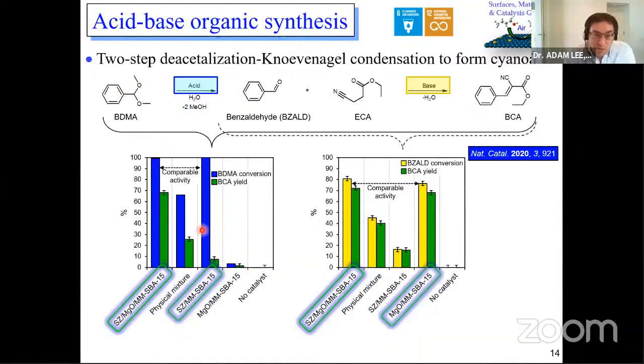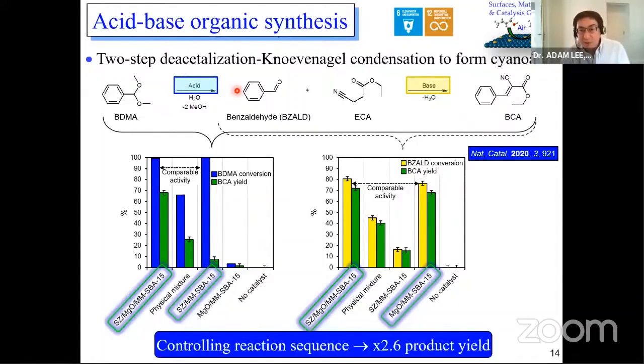And that's why the overall yield of BCA is about 70%. It is far superior to what you see with a physical mixture. So if you just take a physical mixture of a normal solid acid and solid base and put them into the same flask, you get quite poor yields of the final product. Whereas here, bringing these two sites, the acid and base site, close together allows us to do the cascade very effectively. So again, an acid and base reaction there. I'll show you another one. We can achieve more than double the product yield by doing that.